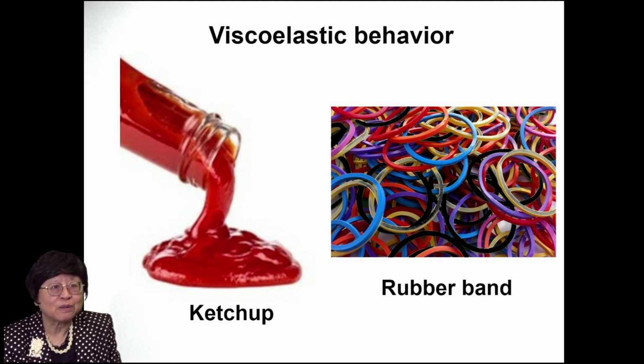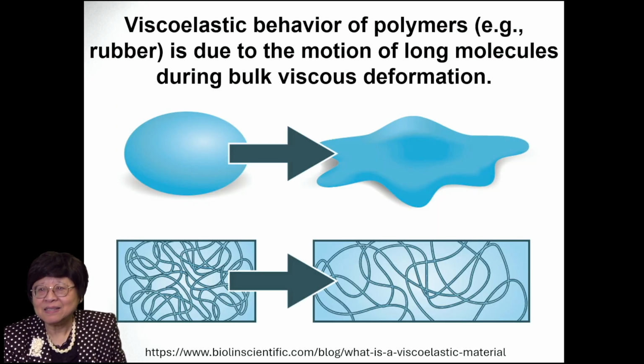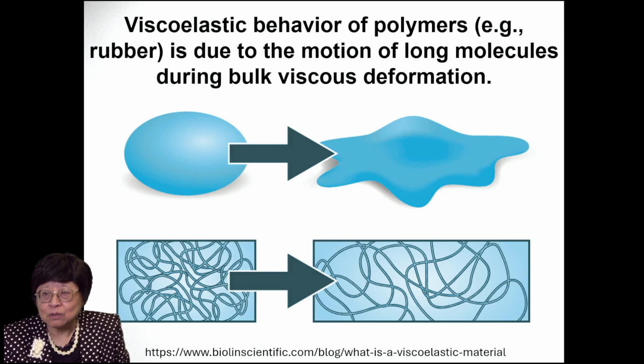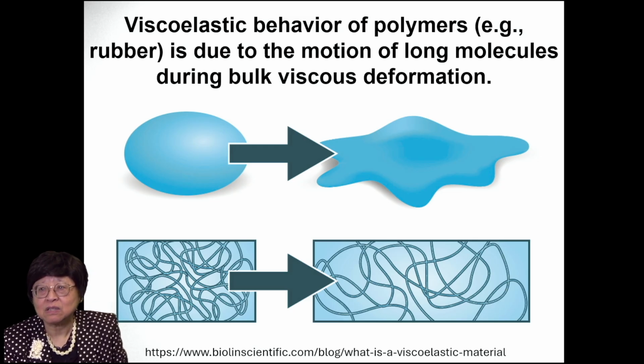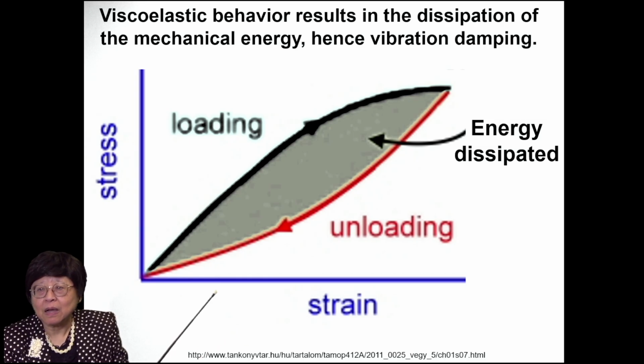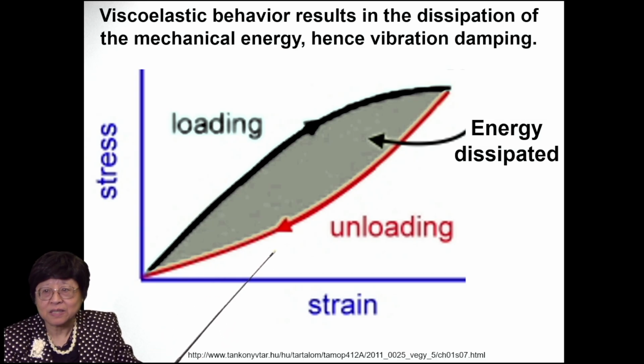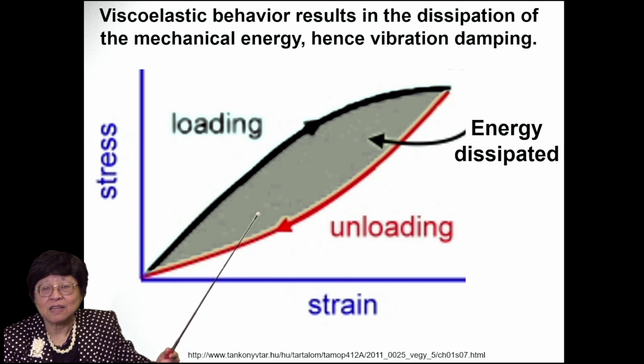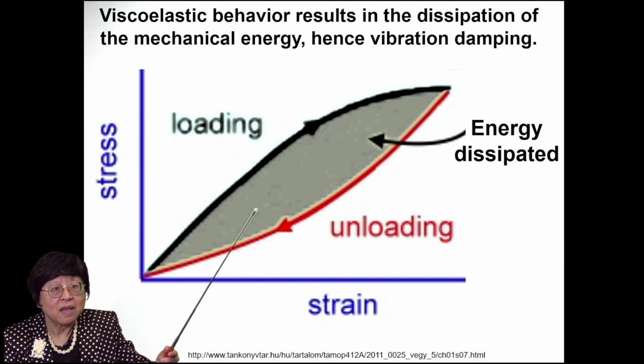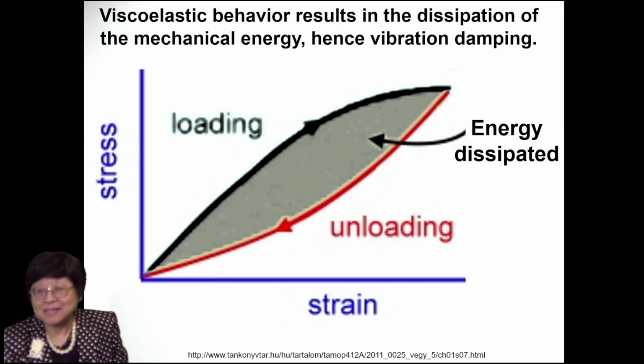Viscoelastic behavior of materials is the key to vibration damping, like ketchup and rubber band. And the idea is that, say you have rubber, and inside the rubber there are long, long molecules. And when you deform the rubber, there's motion of these long, long molecules, and that motion consumes mechanical energy, thereby reducing the vibration. The stress-strain curve upon loading doesn't overlap that during subsequent unloading, and so there is energy dissipation. The bigger is this hysteresis loop, the better. This is viscoelastic behavior.